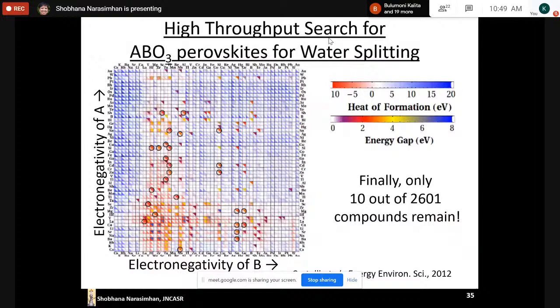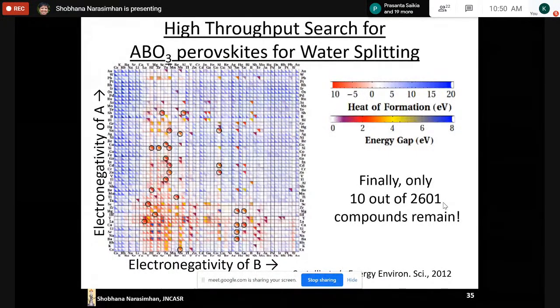So here is this calculation that people performed, again on a class of materials called perovskites. These are ABO3 perovskites. And these are all possible sources for the A metal on one axis and all possible sources for the B metal on the other. And they did calculations on these 2,601 compounds. And they calculated the heat of formation and the band gap. And when they finally calculated these two quantities, only 10 out of these 2,601 compounds remained. And once you have narrowed this down to these possibilities with the calculation, then the experimentalists can try to make only these 10 compounds.